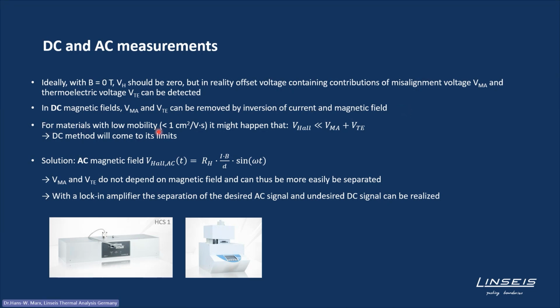But for materials with low mobilities, it may happen that the Hall voltage is much smaller than the offset voltages. And in these cases, the DC method comes to its limit, and you have to use the AC magnetic field. The AC magnetic field is shown here, the equation. And the misalignment and thermoelectric voltages, so the offset voltages, do not depend on the magnetic field and can be separated. And this is done by separating the AC from the DC signal with a lock-in amplifier.